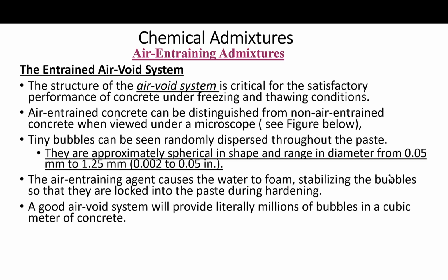They are approximately spherical in shape and range in diameter from 0.05 millimeters to 1.25 millimeters. So it looks as if the paste has been blended with a fine foam, and this is essentially what happens. It's just like a foaming agent we add in order to create these bubbles.